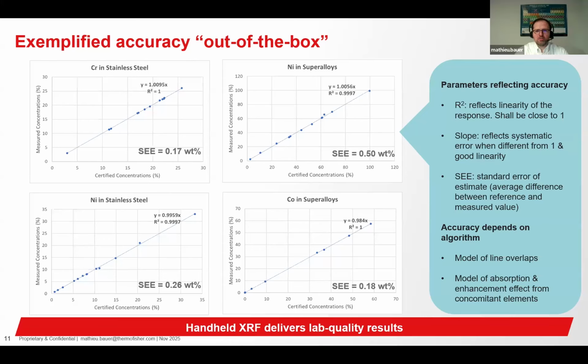This slide illustrates the results obtained out of the box for sets of certified stainless steel samples, as well as a set of superalloys, which are alloys with cobalt and nickel as the base elements. For all four cases, as you can see, there is an excellent correlation between the certified values and the measured values, given by the R-square correlation coefficient, as well as a slope close to 1, which indicates a very low systematic error or bias.